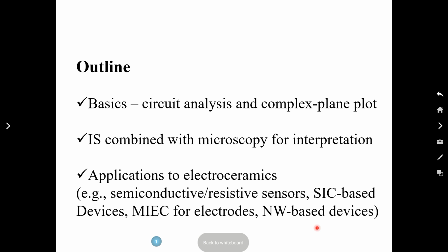And you can collect those in a suspension, like water or some salt, in liquid medium. And then you can take a pipette, micropipette or some sort of pipette, and just put it on a platform. If you have a substrate with interdigitated electrodes for electrical measurement, you can pipette some of that suspension, dry it out, and fire it, so that they will basically be sitting on top of the platform.